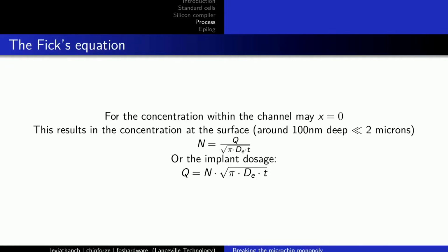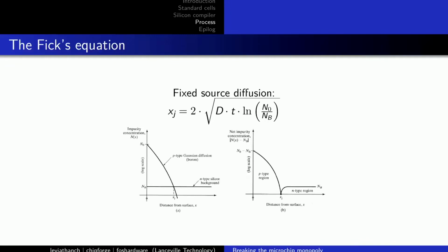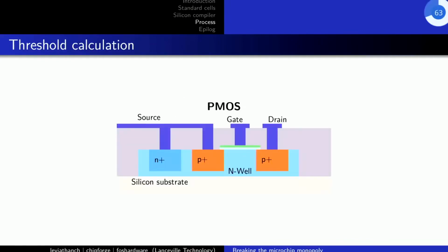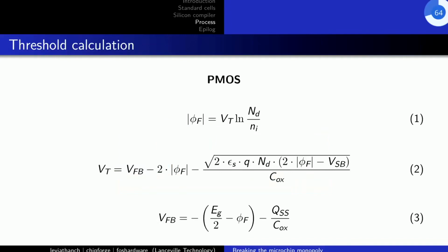So yeah, those are the equations you see here with background doping. It's a little bit much. You have this natural logarithm inside, but besides that, you see this jump, and that's how you essentially build a well. You have the background doping, and you compensate donors and acceptors with each other. That's what this absolute value of the difference means. So the threshold equation is pretty easy, and they are basically mirrored for PMOS and NMOS, in the sense that PMOS is built on an N well, and NMOS is built on a P well, right?